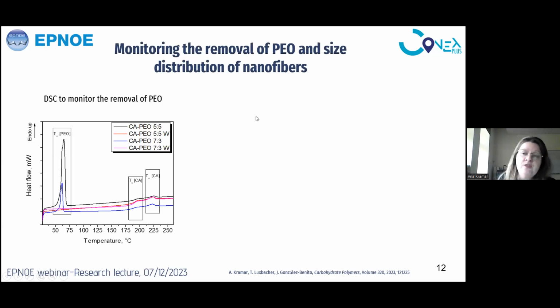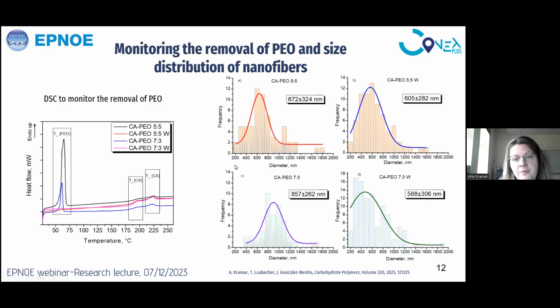We decided to use differential scanning calorimetry to monitor the removal of polyethylene oxide. That's how we were tracking the removal, and that's how we saw that we removed the majority of polyethylene oxide. So you see here we have peaks that correspond to the melting temperature of PEO, and after washing, these are the samples denoted W as washed samples, this peak is disappearing.